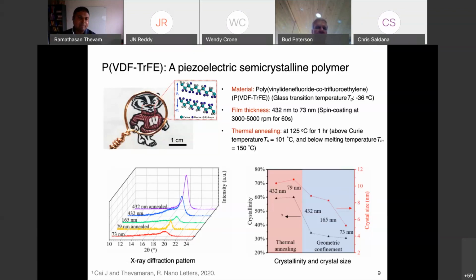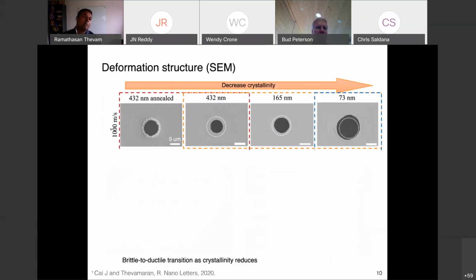If you take this material and shoot it with microprojectiles at high velocity, about 1 kilometer per second, the dotted line shows the projectile diameter. As you go from the annealed film to the thin film, you have decreasing crystallinity. The strain is much more localized in the annealed film, and the deformation gets more and more delocalized as you go to thinner films.